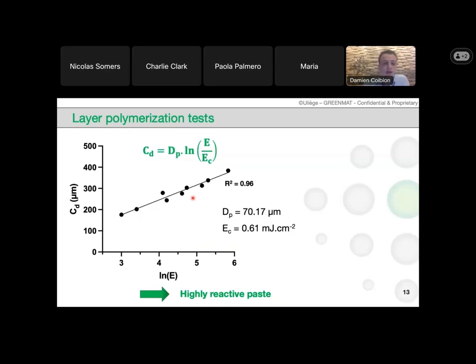So we can plot this kind of graph with the curing depth as a function of the energy density. And from this graph, we can find some information. The first one is the penetration depth. So it is the penetration of the laser until it has 37% of its initial energy, and also the critical energy density, which is the lowest energy required to print our paste.